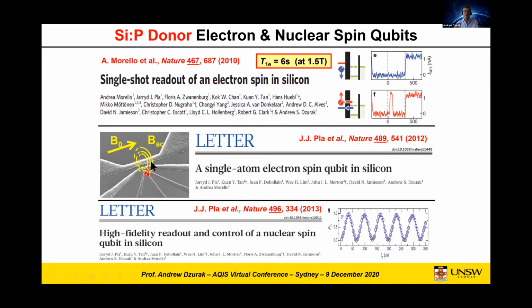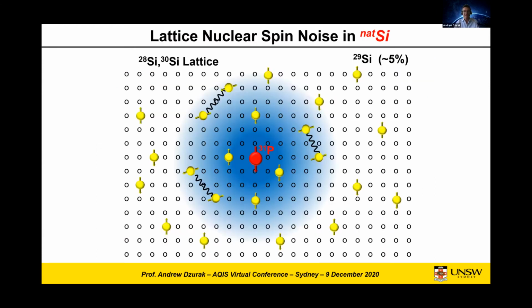In the gigahertz regime, we perform electron spin resonance to control the electron spin. In the megahertz regime, we perform nuclear magnetic resonance to control the phosphorus-31 nuclear spin. With these demonstrations, it really showed that it was possible in nanoelectronic devices to control individual spins on individual atoms for the first time, essentially atom-based electron spin resonance and atom-based nuclear magnetic resonance. Now, one of the challenges still at that time was that the electron spin Rabi oscillations were not very good. Fidelity of those was really only around 70% or so, quite poor.